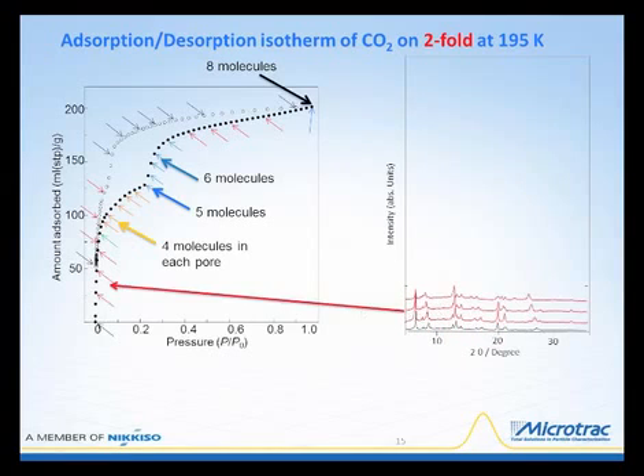So as we go forward, and adsorption is occurring, and remember, this looks like there's really no change in the adsorption at virtually zero relative pressure. But as I showed you before, with a log representation of this, there is actually a very slight change in the relative pressure leading to adsorption within the structure. And we're seeing that starting to occur here because there are changes already occurring during the early parts of the isotherm development. And we can see these changes starting to occur. And I'm going to go through this a little bit stepwise.